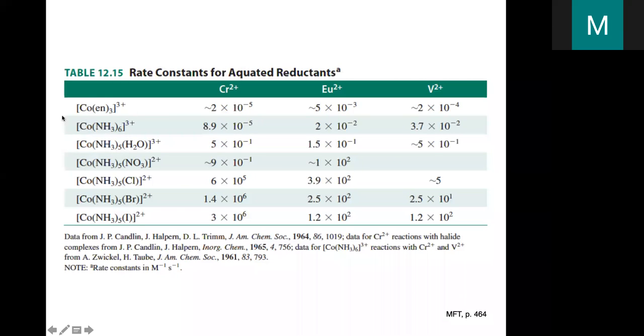So for cobalt trisethylenediamine and cobalt hexammonia 3+, neither of those ligand types can form a good bridge with any of the reductants, either chromium, europium, or vanadium. And so presumably those reactions would have to proceed through an outer sphere mechanism. And so those are the slowest rates that we see here. And then water and nitrates can form bridges, but they're not very good bridging ligands. And so they show faster rates, but not the fastest of the series. The fastest rates are seen for the bottom 3 complexes, where a halide ligand is very well suited to form a bridge to the chromium, europium, or vanadium center and enable the inner sphere pathway.